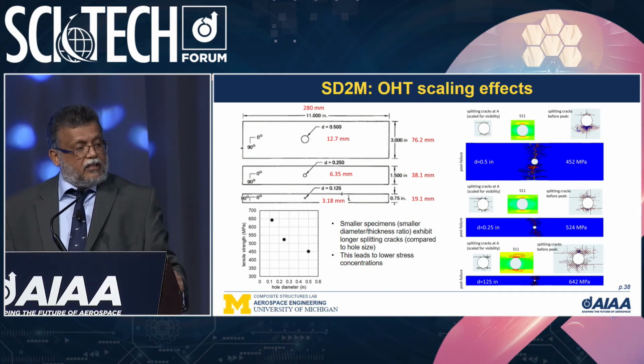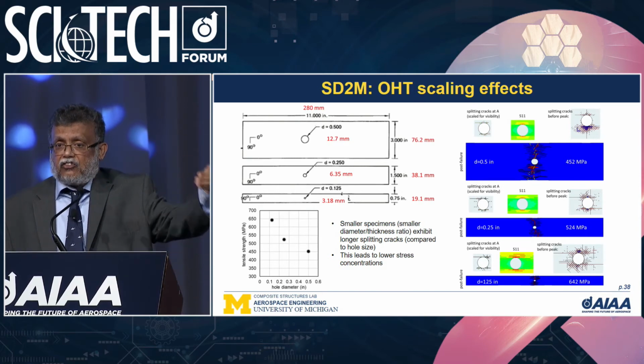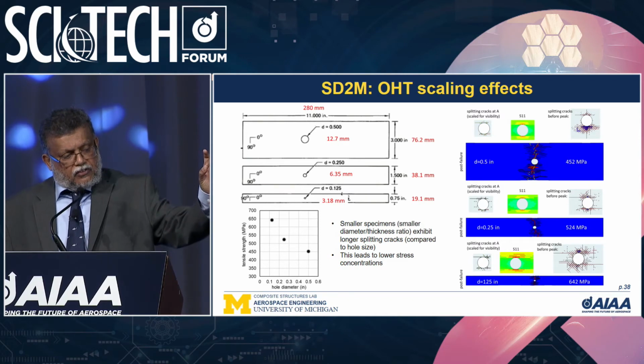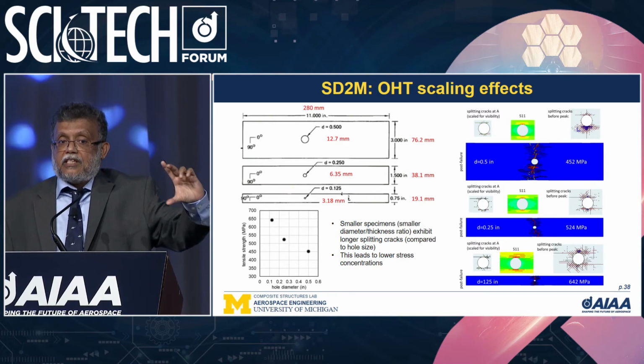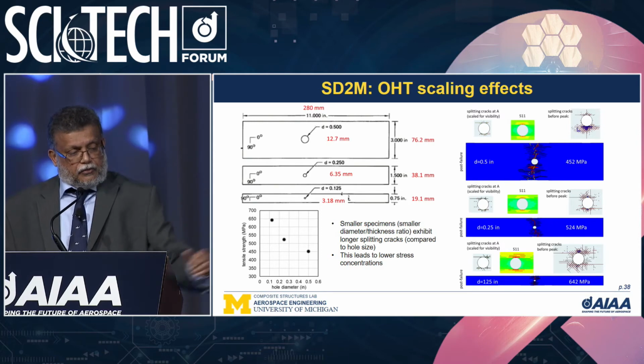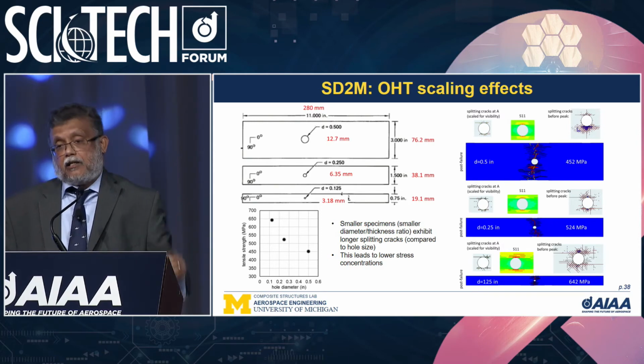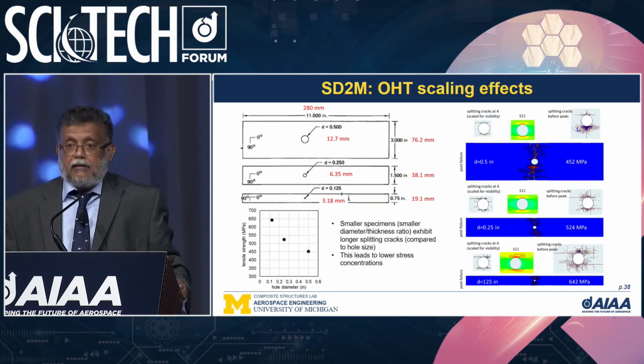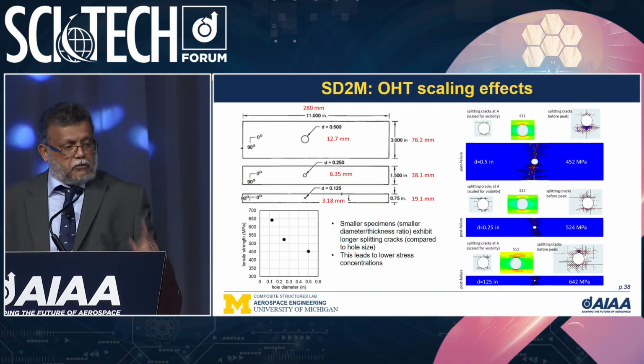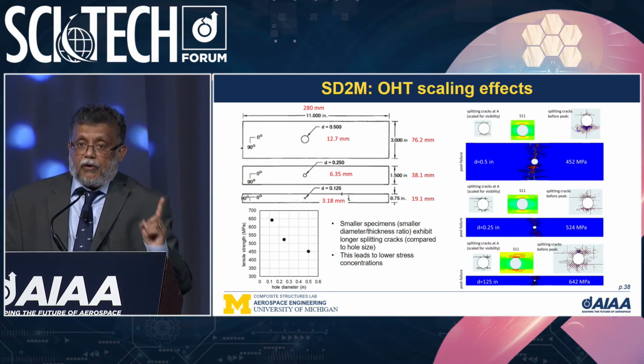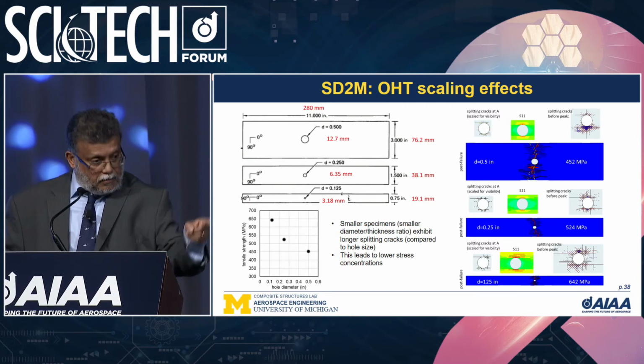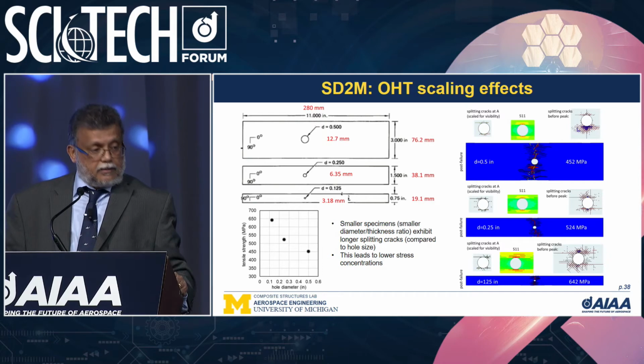Here I am showing you results where we kept the scales the same, so the ratio of the size of the hole to the width is kept the same. These tests were done at the Boeing company. We are able to capture the notch strength, hole diameter trend that you see in these types of laminates. Furthermore, we are able to capture the failure mechanisms very accurately in all 3 different scale tests. All runs took less than 4 hours.